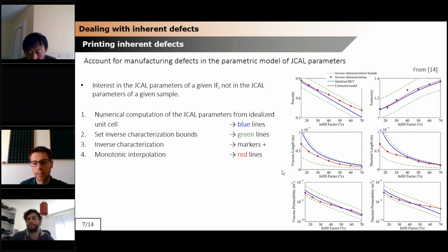And these bounds were set accounting from the numerical results of the defects. So for instance, simulating the defects, we saw that the viscous length tends to decrease when considering the defects. So we said, okay, during the inverse characterization, the viscous length that we'll get from experimental measurement must be lower than the one from the idealized unit cell.